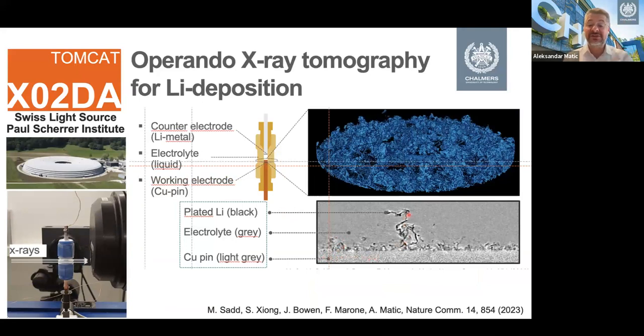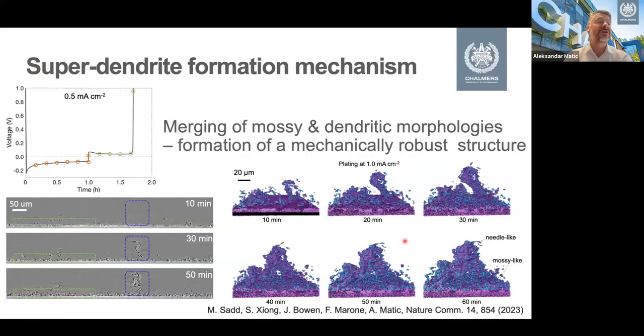And you see all these structures are from lithium. And we could follow how they actually grow in real time, all the time as the cell was cycled. And in this way, what we could then see was, when do we actually form structures which become inactive, which is one of the biggest problems for lithium metal batteries, that fragile structures can break off, become electrically isolated, and in this way stop contributing to the capacity.